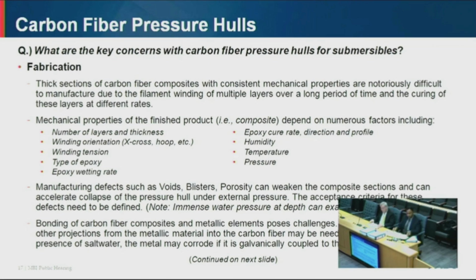Then humidity is another important consideration. So high humidity during curing of the composite can negatively impact the mechanical properties. This is because moisture absorption in the resin can lead to delamination and reduced interfacial strength between the carbon fiber and resin, thus weakening the composite. Then curing the carbon fiber composite at the proper temperature is very critical. So if you don't follow the exact temperature profile when you cure the carbon fiber composite, then it will affect the mechanical properties.